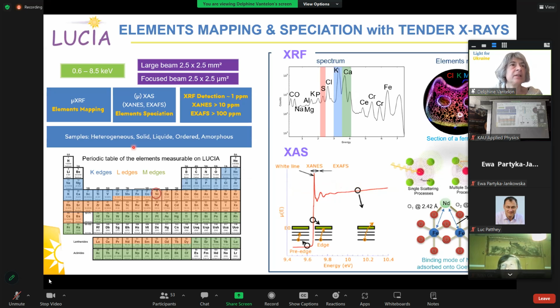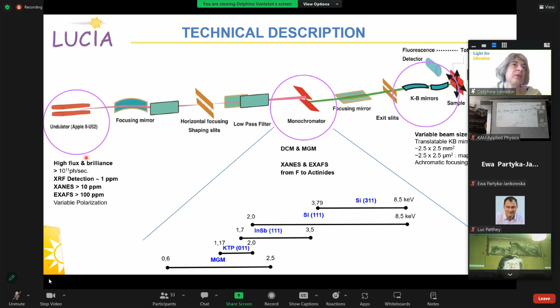And this can be done on samples, as you will see, that are super heterogeneous, so liquid, solid, ordered or amorphous samples. And the detection limit is rather low because the source is an undulator. And also, to cover the whole energy range, the beamline has a monochromator that is composed of a DCM, with several crystals, and a multilayer grating monochromator to cover the low energy range. It is working with a focusing mirror and an exit slit after the monochromator. And then the beam can be focused, translating KB mirrors into the beam as the last mirror optics of the beamline. You can translate them into the beam or remove them from the beam.